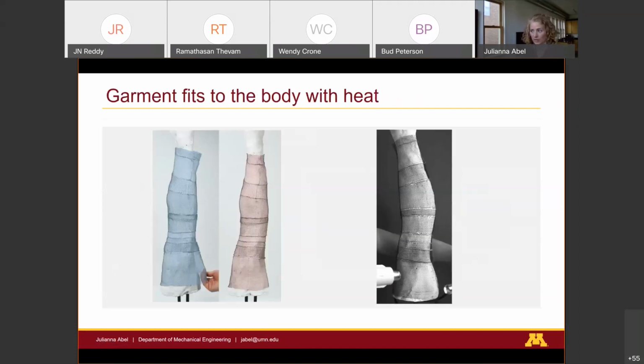And so we actually created this garment. On the left, you can see the image, the stills of it. And on the right, it's made with Dynalloy Flexinol 70-degree C wire. And so it's being heated with 2 heat guns. And you can see as it's being heated, it shrinks and perfectly conforms to this plaster cast leg.